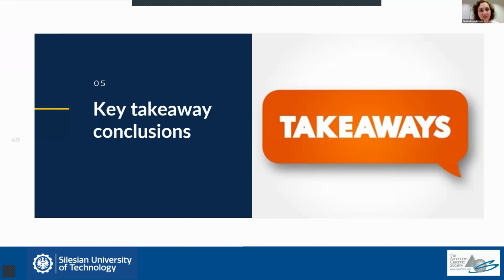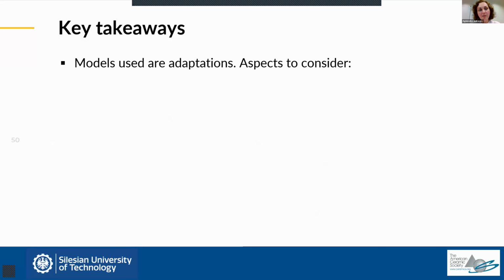So to summarize this lecture, what are the key takeaways regarding design of massive concrete structures which are subjected to restrained cracking? First of all, we must remember that models that we use for design are adaptations. So they are based on the models which we use for thin elements, which are subjected to direct loading. And the aspects which must be thoroughly considered in such models are as follows. First of all, we must take into account the actual cracking stage which we observe. So in contrary to the elements which are under direct loading, here we will never obtain stabilized cracking stage, which has a basic effect on the slip length, which is taken directly in calculations of crack width.